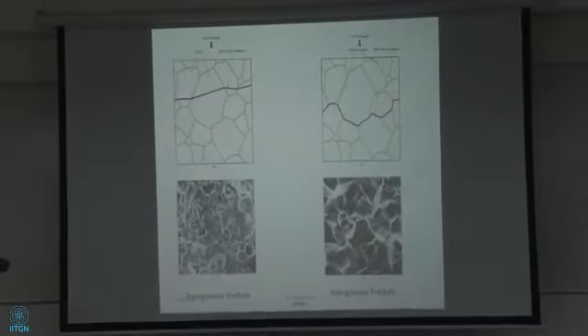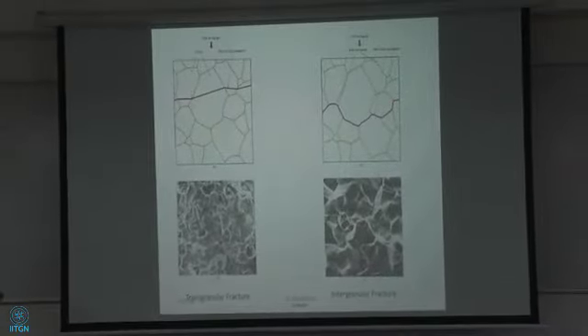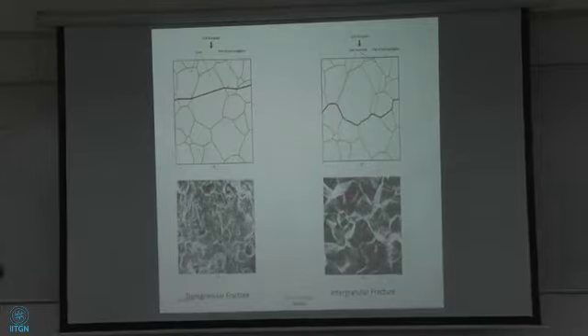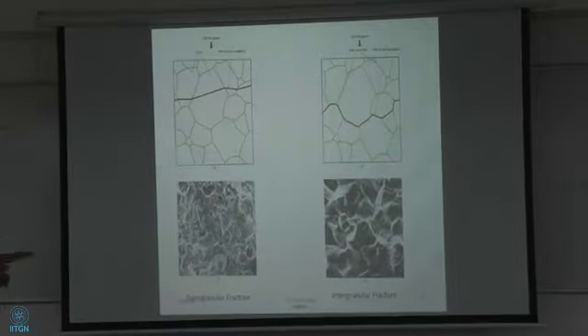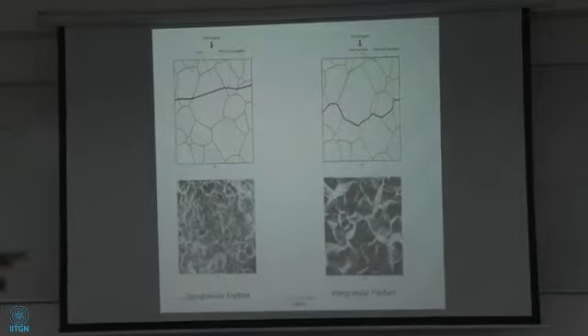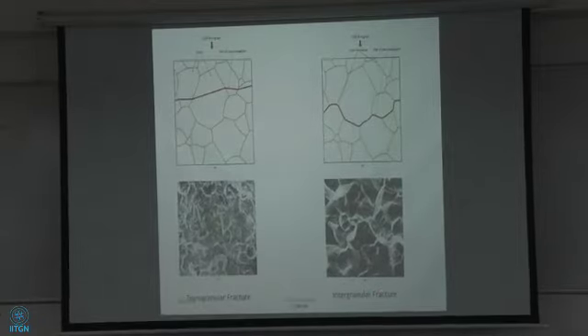Right? And when you look in the scanning electron micrograph, you can really see the grain boundaries right there. These are all grain boundaries. You can see the 3-dimensionality of the grains, right? But here it's very distinct. They both are low energy fractures. I want you to keep that in mind. They both are low energy fractures, but one is a transgranular fracture, one is an intergranular fracture. This is the cleavage, this is the grain boundary cracking, right?